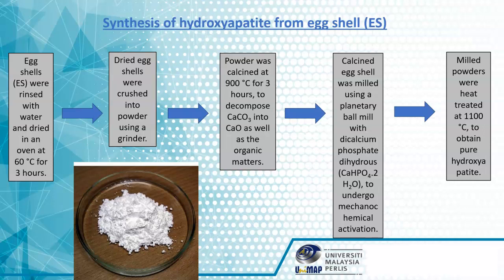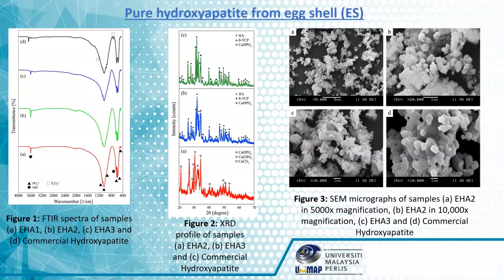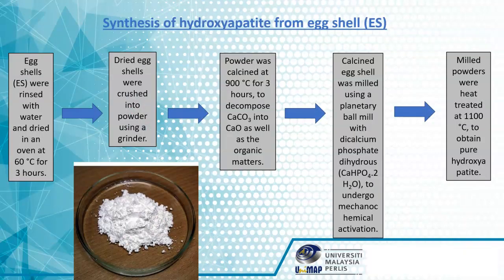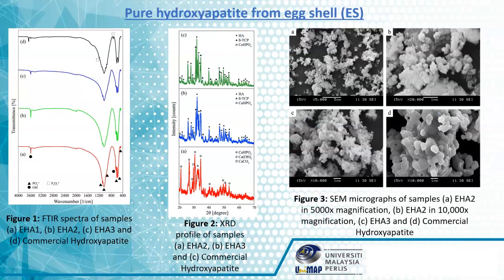For the synthesis of hydroxyapatite from eggshell waste, firstly, eggshells were rinsed with water and dried in an oven at 60 degrees Celsius for 3 hours. Then, the dried eggshells were crushed into powder using a grinder. Next, the powder was calcined at 900 degrees Celsius for 3 hours to decompose calcium carbonate into calcium oxide as well as the organic matters. Then, the calcined eggshell was milled using a planetary ball mill with dicalcium phosphate dihydrate to undergo mechanochemical activation. And lastly, the milled powders were heat treated at 1100 degrees Celsius to obtain pure hydroxyapatite.